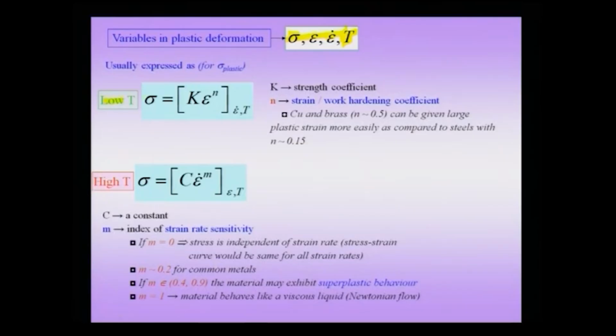At low temperatures you can write, and this is one of the standard equations, stress sigma, which is now true stress, can be written as a constant K into epsilon, which is the strain, power n, and we are assuming this is conducted as a constant strain rate test at constant temperature. K is called the strength coefficient and n is the important parameter, called the strain or work hardening coefficient, or the work hardening exponent. For copper and brass, n is about 0.5. That means this material can be given large plastic strain much more easily as compared to steels, which have a smaller strain hardening exponent.